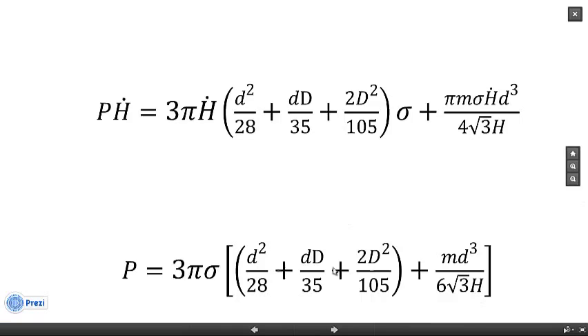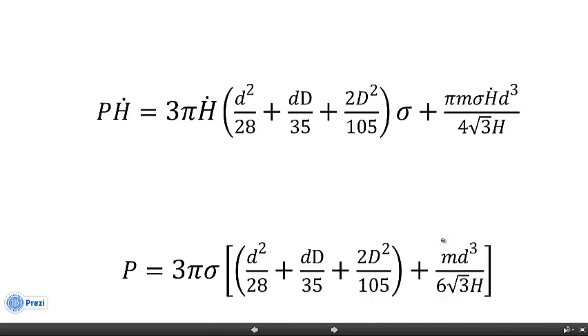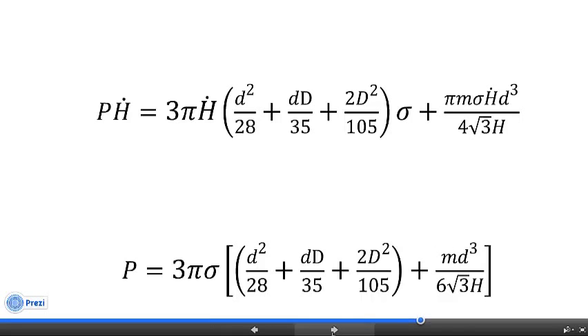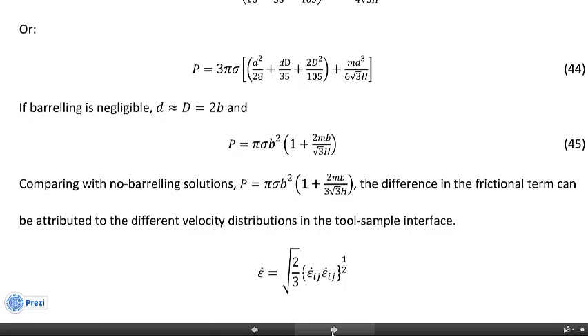Before using this barreling-corrected expression for data reduction — converting load-displacement into flow stress — we must be sure about the friction. Whatever friction we measured by other techniques may not be applicable to this particular test. For a special case this relationship becomes very similar to the conventional solution, except the friction term is divided by 3, which is natural because we used a more comprehensive velocity field.